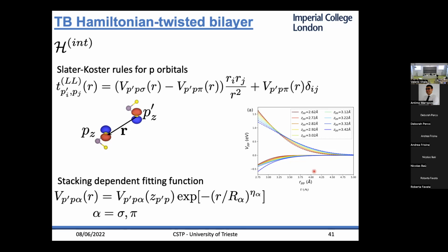But the issue is that in our Moiré structure, we don't have a single interlayer distance, but we have different interlayer distances, so separations, as I showed in the relaxation. So basically, we had to parameterize this interaction for different interlayer distances. And so we came up with a different formula, which was stacking dependent. So it's dependent on this Z, which is basically the interlayer separation between the two layers. And you can see basically you have different exponentially decaying curves for different interlayer separations.